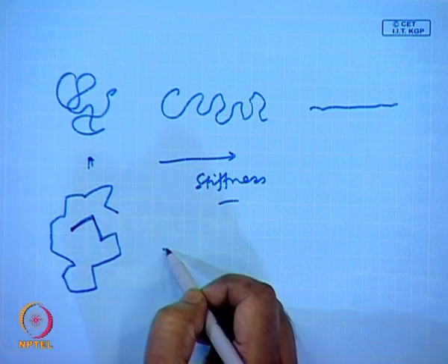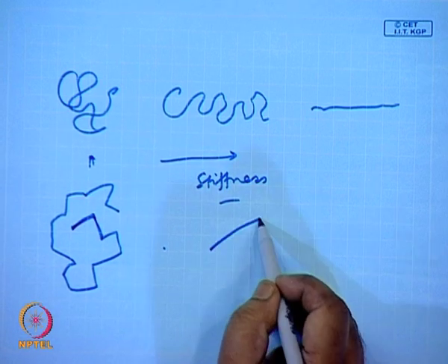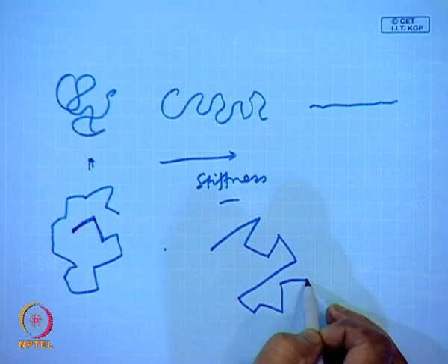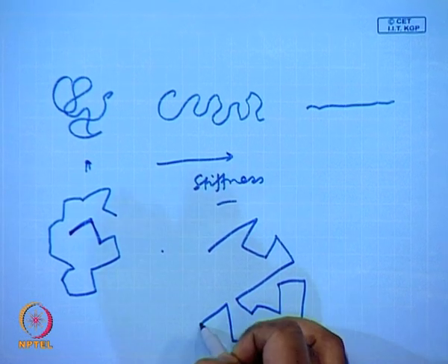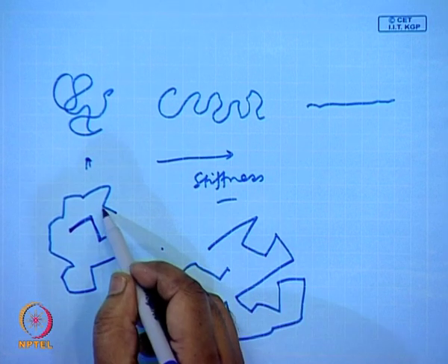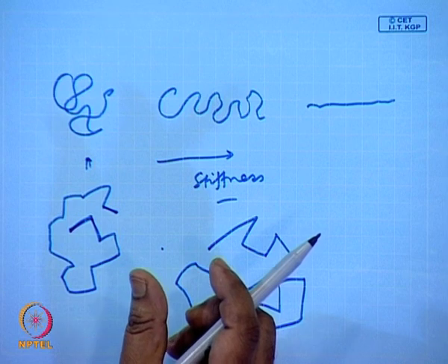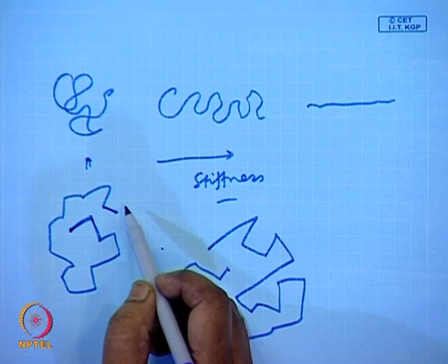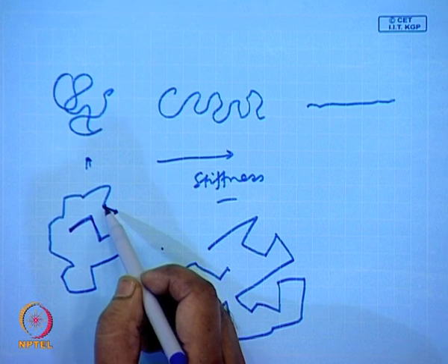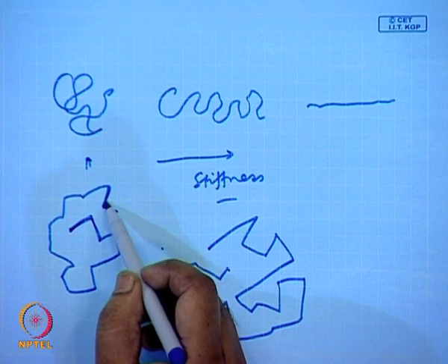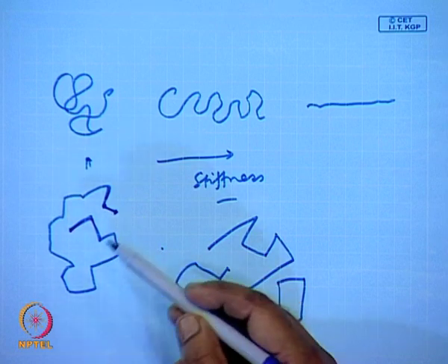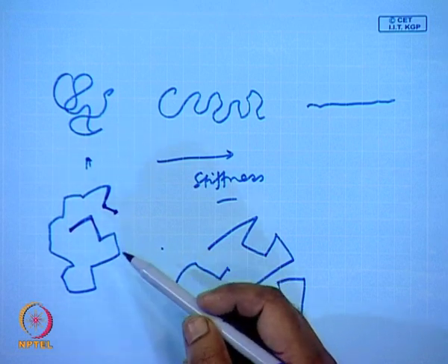Each gas molecule can take any step, wherever it wants and in any direction, but in the case of a polymer molecule, steps are fixed as the bond length of the backbone repeating unit, and there are restrictions of fixed bond angle and also on the rotation.